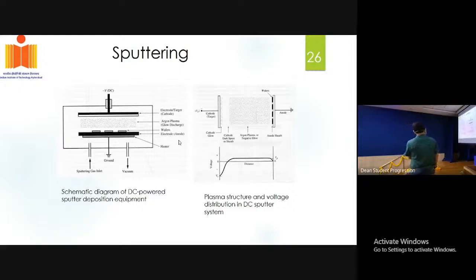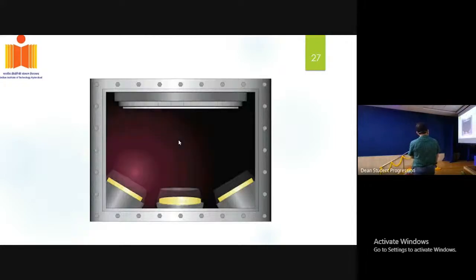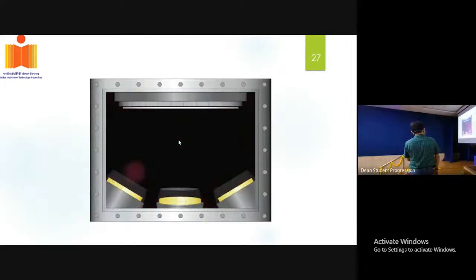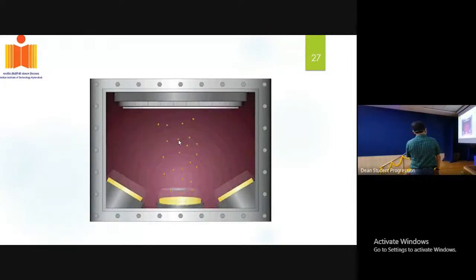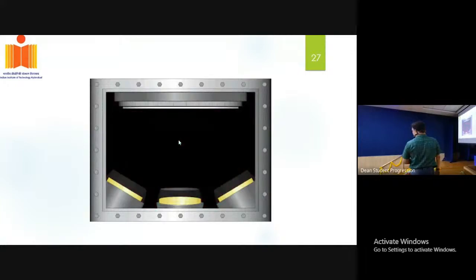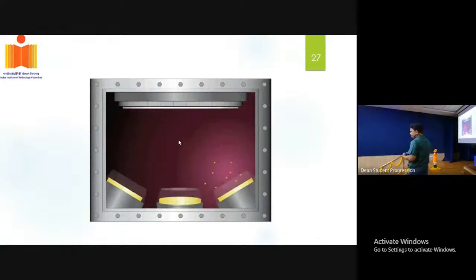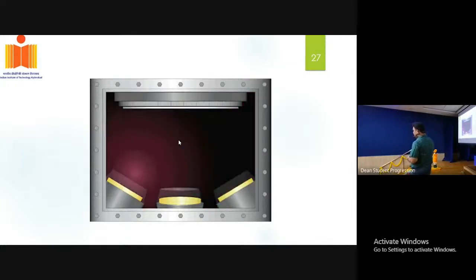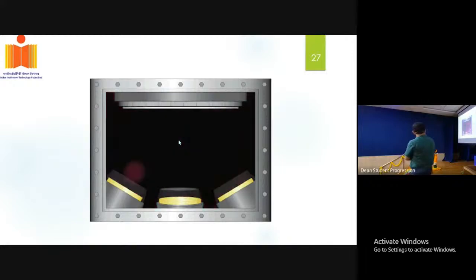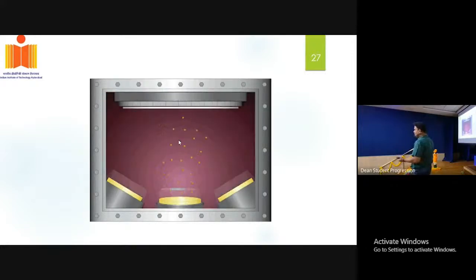So the same thing we do here. We create the argon gas in the chamber and apply the high potential difference, so that argon plasma can be created. So basically, if you see the animation, these atoms will be ejected and will be deposited on top of the substrate. In case of sputtering, or be it sputtering or thermal evaporation, it is very important to get the uniform thin film.